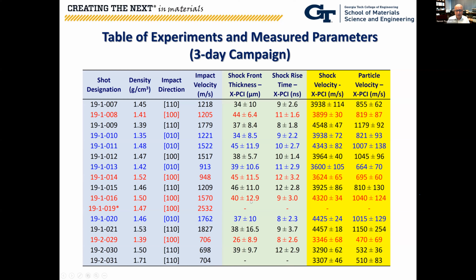These 2 columns in green identify the shock front thickness and the shock rise time. This is interesting - even in this highly composite material, we find that the shock front is fairly narrow, with a rise time of the order of 10 nanoseconds, and a shock front thickness of about tens of micrometers. The right 2 columns are the measured parameters, the shock velocity and the particle velocity. Again, these are in-material parameters obtained from X-ray phase contrast imaging.